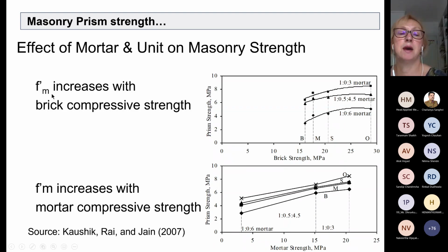In any case, F'(M) increases with brick compressive strength, and F'(M) increases with mortar compressive strength. So both are important, but I would say bricks are more important, particularly for lower strength mortar, as you can see on the upper side diagram. So you can see that for 1/6 mortar, it changes maximum depending on the brick strength. The F'(M) changed to a much larger extent than for the other values.